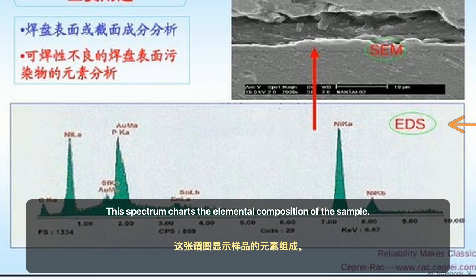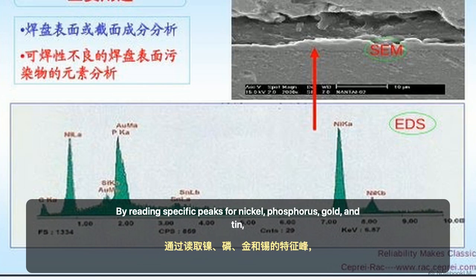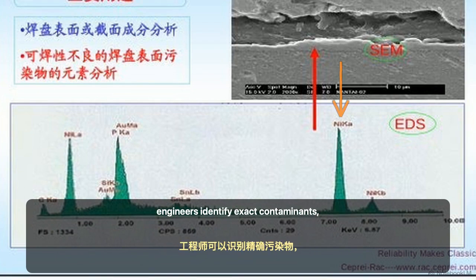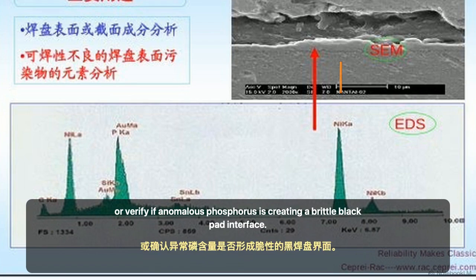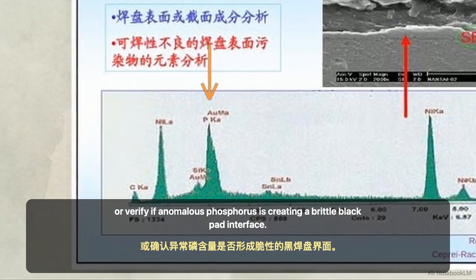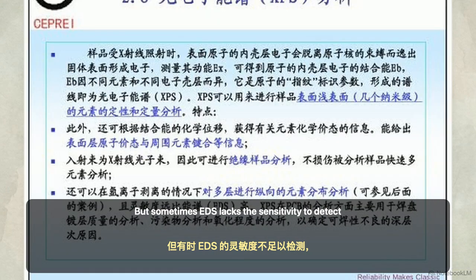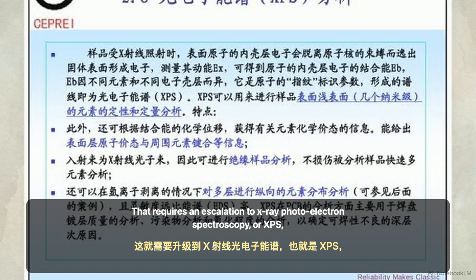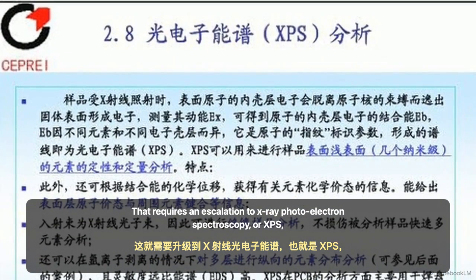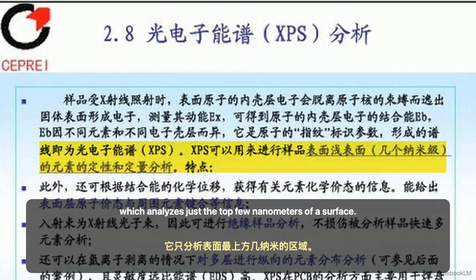This spectrum charts the elemental composition of the sample. By reading specific peaks for nickel, phosphorus, gold, and tin, engineers identify exact contaminants or verify if anomalous phosphorus is creating a brittle black pad interface. But sometimes EDS lacks the sensitivity to detect ultra-thin passivation or organic contamination layers. That requires an escalation to X-ray photoelectron spectroscopy, or XPS, which analyzes just the top few nanometers of a surface.